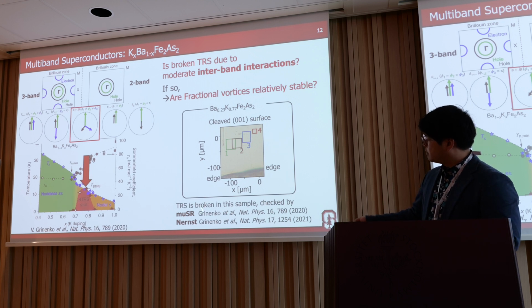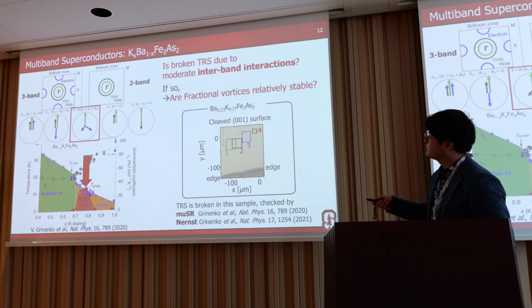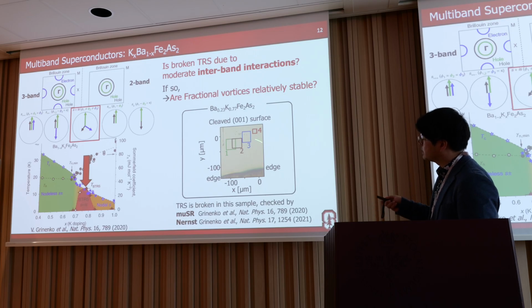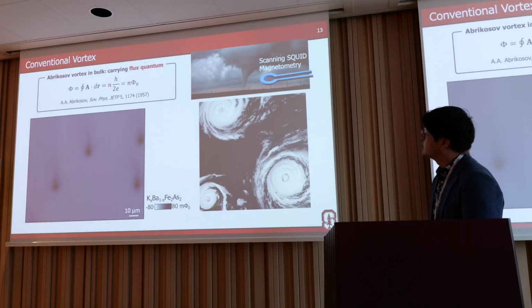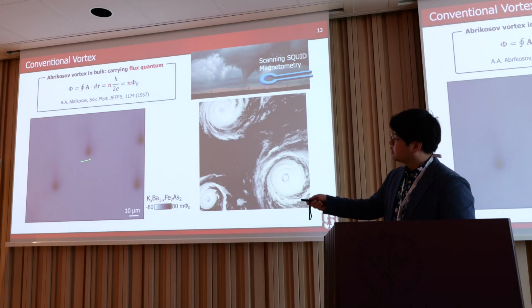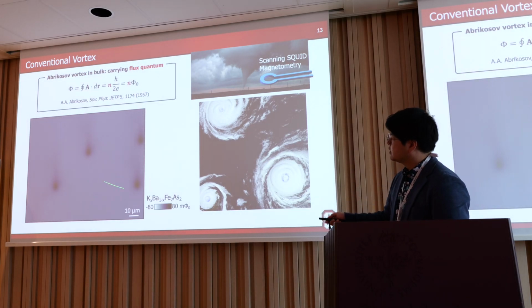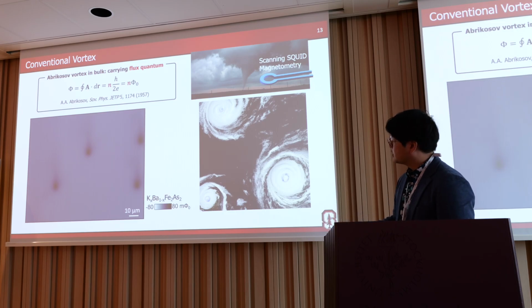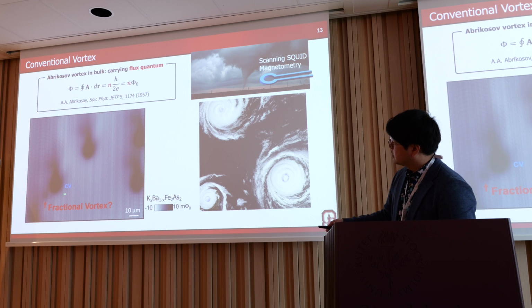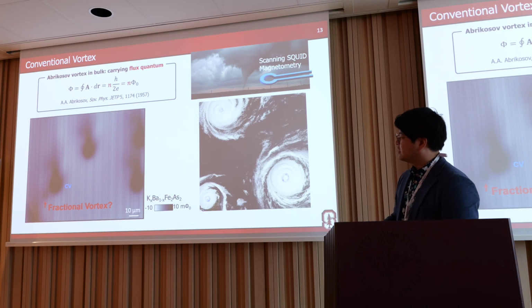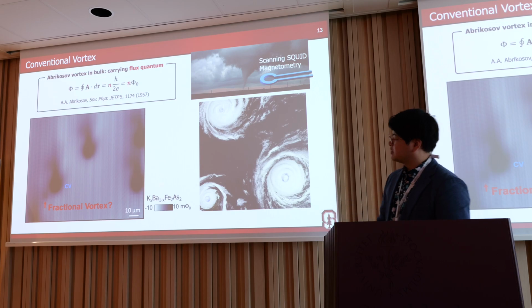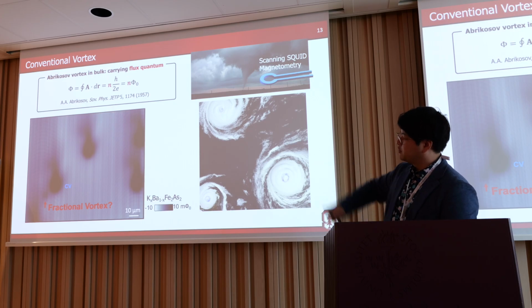After cooling down the scanning SQUID measurement on this sample, we get many crystals, and they are placed on one surface, and then we scan these four regions. It's over the 100 micron scale. I already showed that the integer vortex is observed in this material. But when I change the color scale, there's a tiny signal there. It's like a fractional vortex, but from this one, it's very difficult to distinguish whether it's just a magnetic impurity, or even just dust on the screen of my computer.